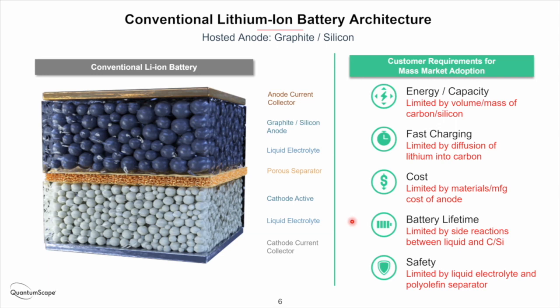is that one of the main reasons that battery capacity fades is this SEI growth continues as the battery ages. And each cycle, as the graphite expands and contracts, this SEI can crack and then regrow, which consumes electrolyte and lithium from the cell. And then in terms of safety, well, this liquid electrolyte and the polymer separator and the graphite material are all flammable components. So they all store energy that isn't useful energy that can be used to drive the car, but store energy that could be released in the form of a fire if the car gets in a crash. So really the anode contributes to all five of these metrics that would be important.